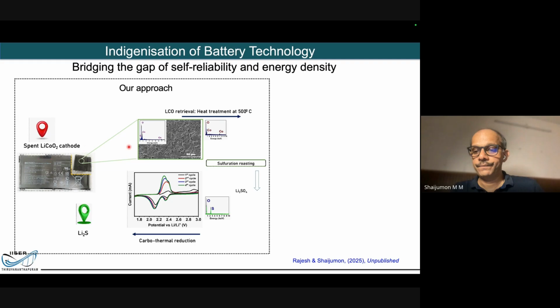And what he did is take out this one and add some metal sulfate solution to it. Simple chemistry. You can imagine the amount of chemistry that I can afford to; I'm from a physics background. So very simple chemistry. It gives you lithium sulfate, and then finally, using a carbothermal reduction, he gets something called lithium sulfide.